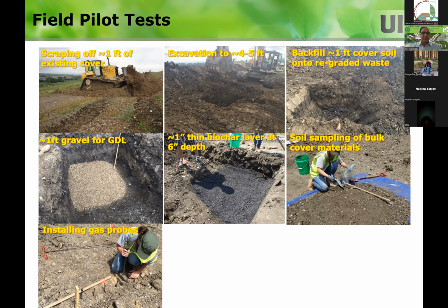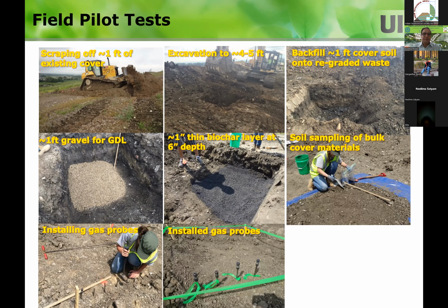And then we put the gas probes at different depths, and then you have these, see on the top you have a port that you can use to collect the gas, and this at the bottom of these probes is at different depths, so you can collect the gas samples. Like in the column, we collected at different depths, right? In the field, how do you do it? So you have these gas tubes extending to different depths, and then we collect the samples from different depths, and we can look at it.